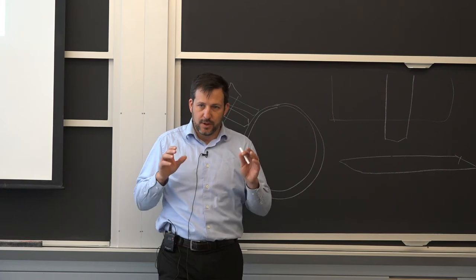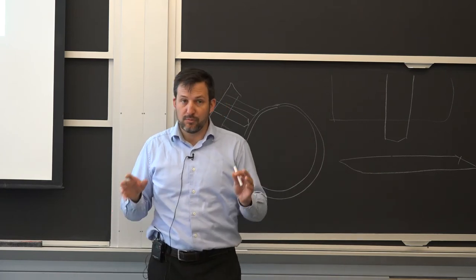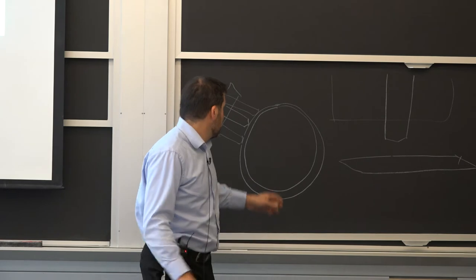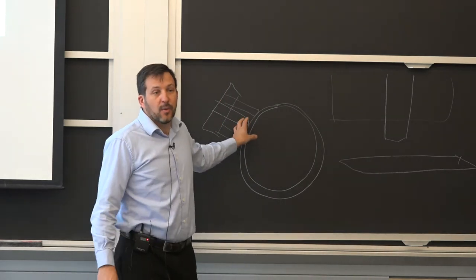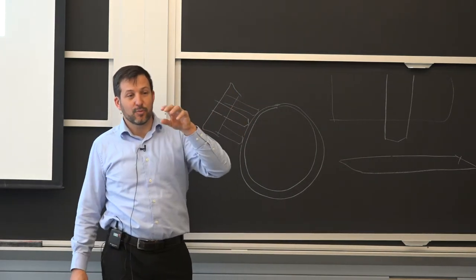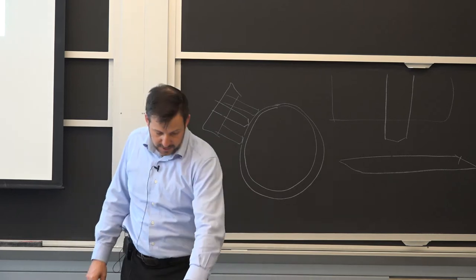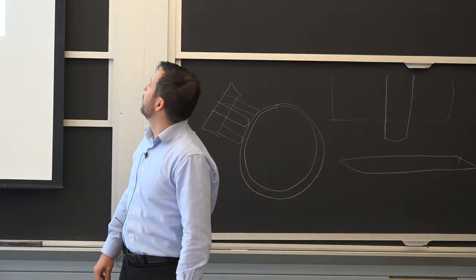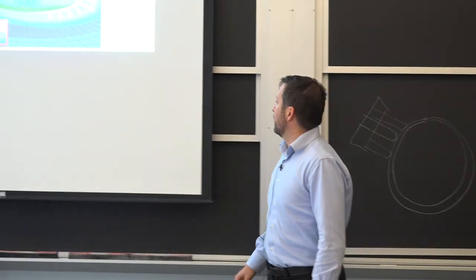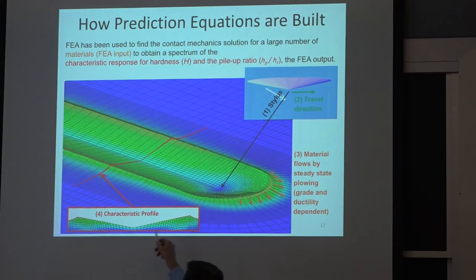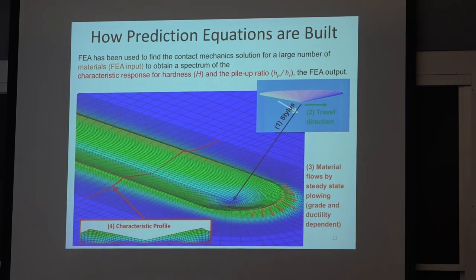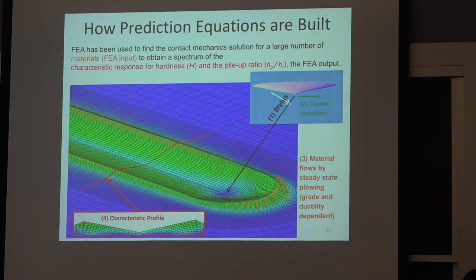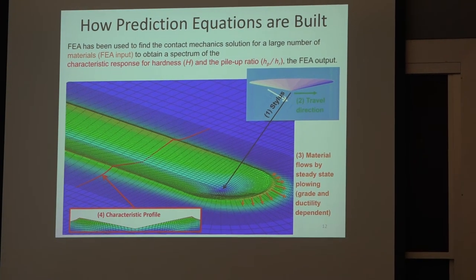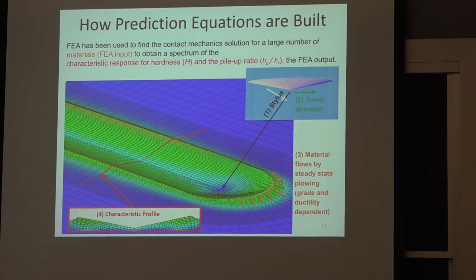So this is all done in the computer. So when we run the test with our special equipment, we're able to translate the raw data that we get, and that's what we collect. We collect essentially the width of those grooves that we make. So that profile here, from peak to peak. We used to look at depth, we don't anymore, it's too complicated for the moment. And we use that information to get our values.